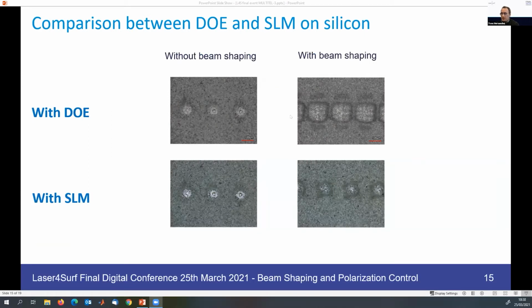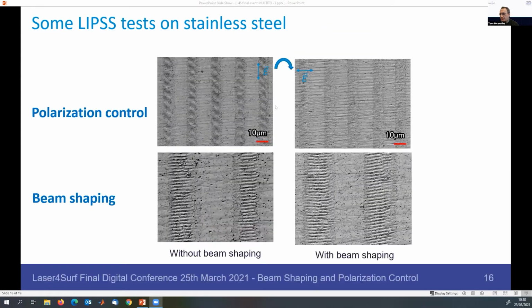Just some comparisons that we did here in the lab with the DOE and SLM. We made some tests on silicon first, just to check the homogeneity of the patterns, so without beam shaping and with beam shaping in the two cases. And we also tried to make some LIPSS experiments on stainless steel. Here you can see on the first two images the polarization control. So here you turn the polarization in function of the direction of the beam, and you can see here that we have LIPSS that are transverse to the beam, and here LIPSS effects that are longitudinal to the beam.